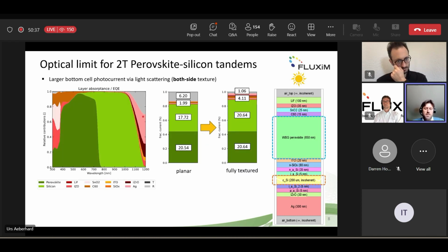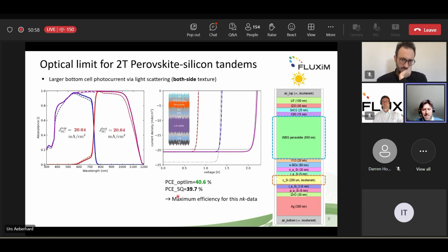Again, we can have a look now at the situation regarding the losses, and we see that indeed the reflection loss is strongly reduced. But as Erkan also mentioned, there is now room for improvement regarding the parasitic absorption, especially at the rear side, for instance, in the silver. Now we find that we actually exceed now the detailed balance limit. So maybe this is not such a good limit after all, because the assumption of this unrealistic absorption seems to be non-ideal for the tandem configuration. And this is actually the maximum efficiency that you can achieve with this NK data if you only change the perovskite thickness.